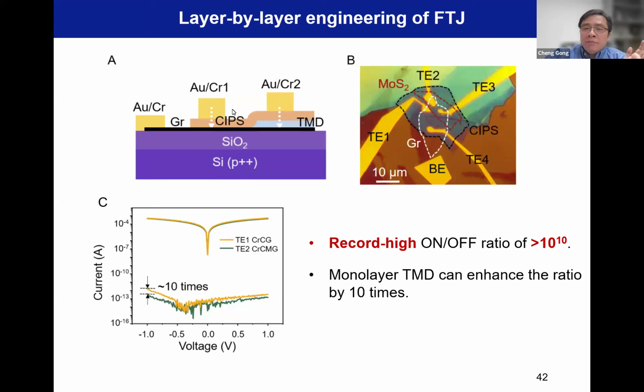When we built this chromium CIPS graphene FTJ, we achieved 10^9 on-off ratio. And when we just put one layer of molybdenum sulfide in between the chromium CIPS and graphene, it further enhanced the tunneling electroresistance to 5 times 10^10 at room temperature. And it's worth mentioning that in the traditional FTJ field, the FTJ is built based on oxide ferroelectrics. And the best on-off ratio at room temperature is just 10^6. So here is a 3 to 4 order of magnitude enhancement.